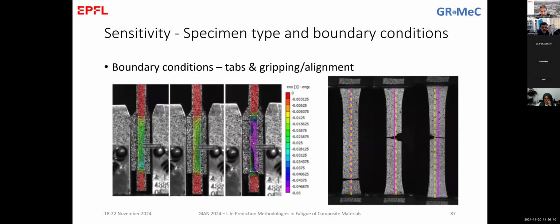So we continued the investigations to see the sensitivity to the boundary conditions, the specimen alignment, and we've seen that it is very, very significant to be careful when we make the specimens and when we put them in the machine. What I show here are actually DIC measurements of the strain caused in the specimen during gripping. You see, these are the grips of the machine, the specimen in the machine, and the strain. So the first two on the left are relatively good. The third one shows stress concentrations.